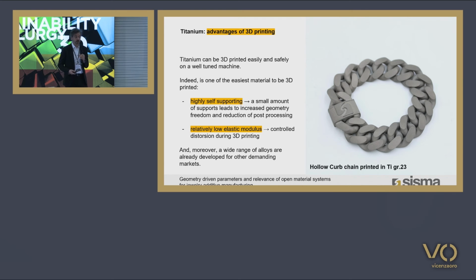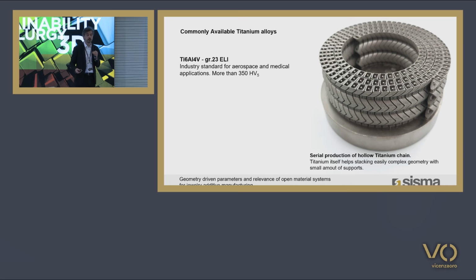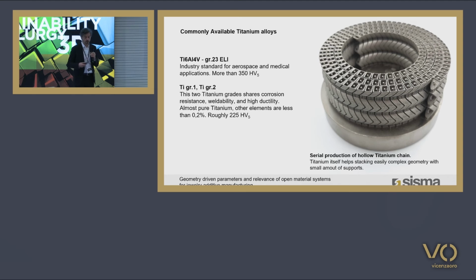And a wide range of alloys are already developed for other markets. If we look at all the alloys available, we have, for instance, Ti-6Al-4V, grade 23. It's quite hard, so it might be difficult to polish manually, but it's really a benchmark material for the whole additive manufacturing industry. We have titanium grade 1 and grade 2, almost pure titanium. The hardness is lower, and it's really interesting for small jewelry shops.